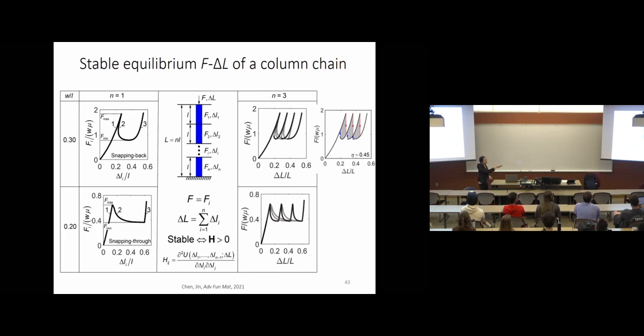Then for a given column, under a given force, there are 3 corresponding displacements. Now I have n columns, so I need to solve this combinatorial problem, right? Each column can be in 3 different possible states. Therefore, I can plot all the possible displacements and obtain many branches of these curves. But not all of them are stable. I need to further study the Hessian matrix to determine which branches are stable, indicated by this solid curve, and which are unstable, indicated by this dashed curve. Then if I connect those neighboring stable curves, I can obtain this loading and unloading curve.